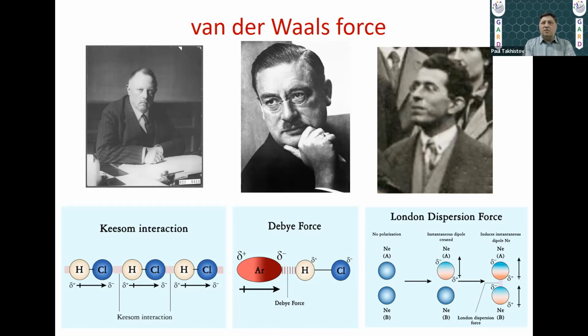The London dispersion forces are the weakest by magnitude but largest in the number of molecules involved, the most common, and they contribute about 60% of all intermolecular forces. I'd like to note that all these intermolecular forces have a common name: van der Waals forces. They exist in all materials and they're always attractive. This is why we have liquids as liquids and solids as solids, just because of van der Waals forces.